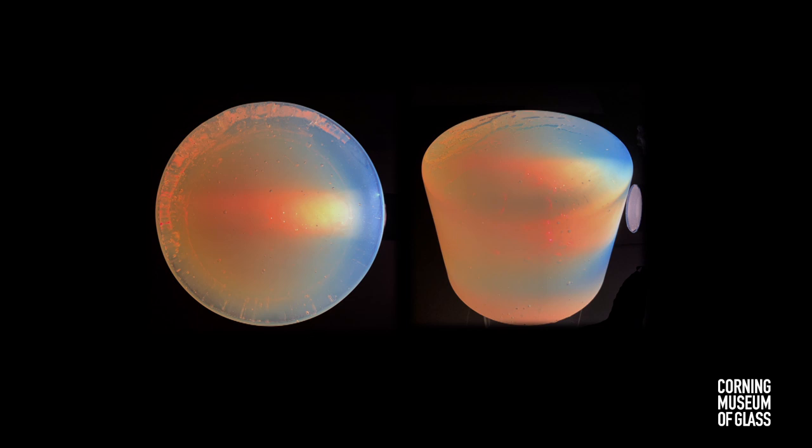Here is a picture showing the colors of light being scattered in Jesse's glass. This boule is three and three-quarter inches in diameter. You can see that in perhaps four or five inches, there would be a red color developed. In our glass, red would appear in maybe nine inches, but at that distance the light is almost all filtered out. The impression I get from this glass is hard to describe — it's more transparent, if you can say that about an opal. It just seems brighter. If it were sound, it would be more like flutes than oboes. Jake and I were both excited to see what this glass would do in a piece.